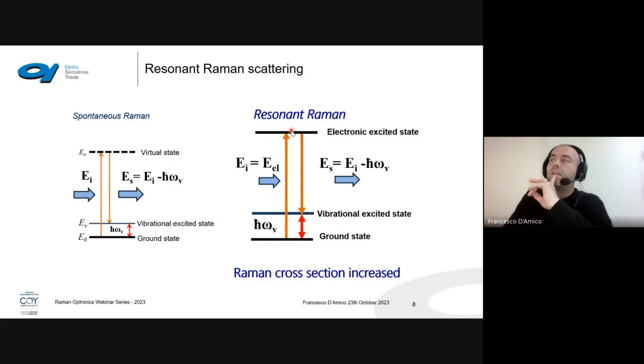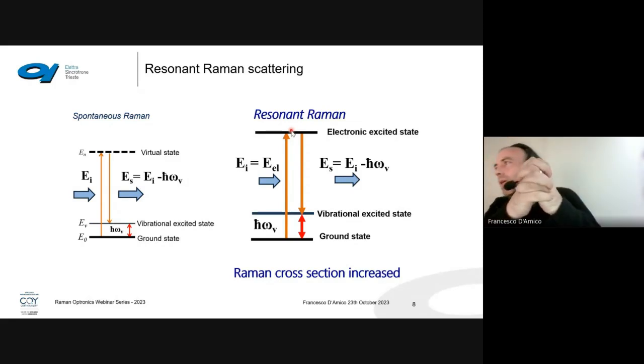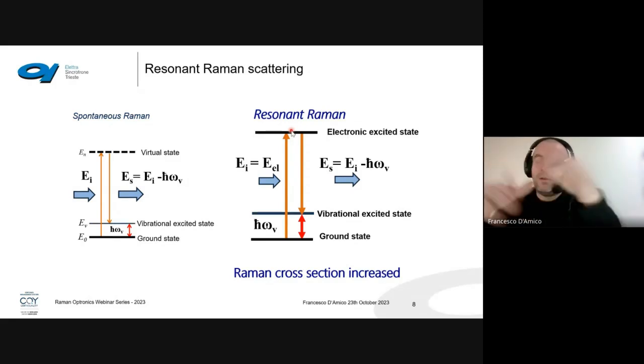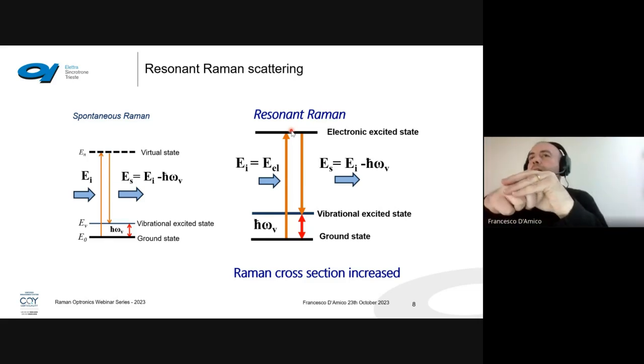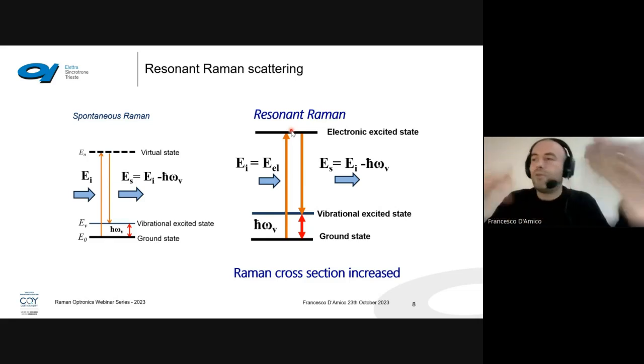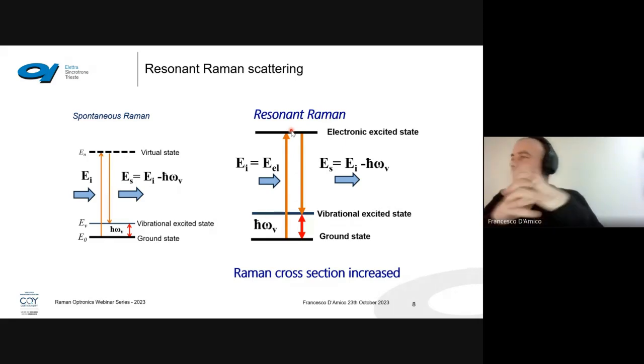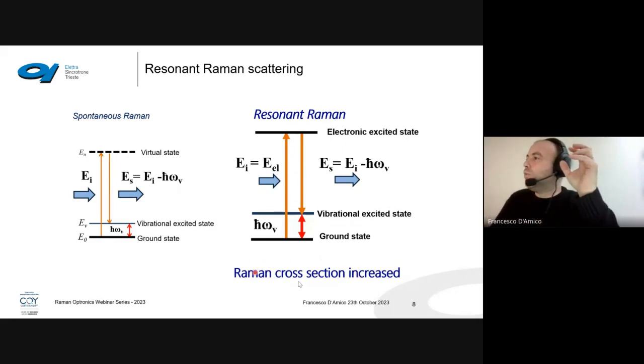It means that in the case of a complex system with a huge number of molecules and different chemical species, if we have a strong increase of the resonant Raman cross section, for example with these two kinds of samples, one which is only spontaneous and one which acts as resonant Raman, we will see in the spectrum only the molecules belonging to the ones that have this effect.